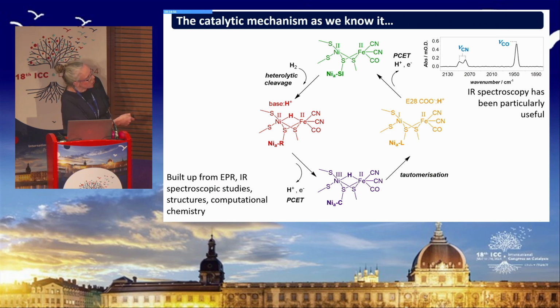There is then a tautomerization step where the hydride leaves as a proton onto again a nearby base, and the nickel is reduced down to nickel-1. The base for this step is likely to be the carboxylate side chain of a glutamate residue, and I'll show you later how we have direct evidence now for that glutamate being involved in proton transfer.